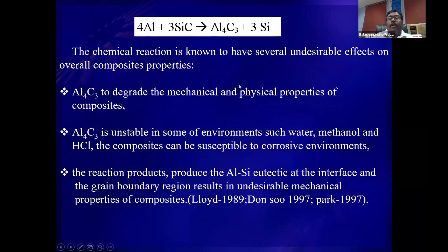And not only that, if you try to control this formation during your processing, sometimes in the working environment, if you have a humid condition or some kind of acidity condition, or an elevated temperature condition, it tries to form Al4C3. So you cannot avoid this. Somehow or other, this byproduct will be formed, either during the processing condition or during the service condition. Therefore, one way to stop this degradation or Al4C3 formation is to coat the particle.